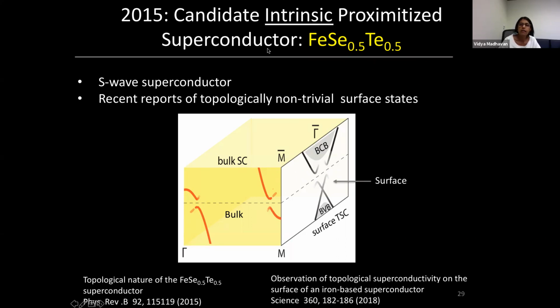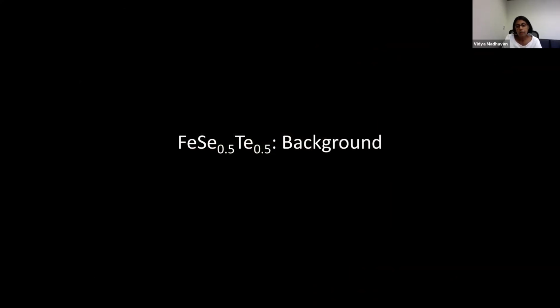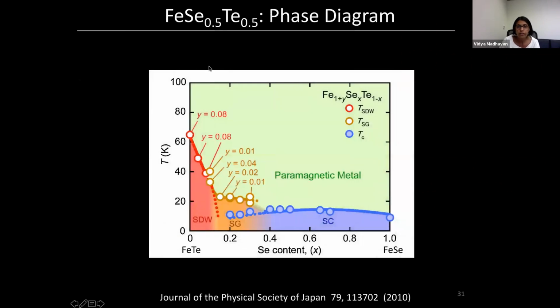So we've known for a long time that this material is an S-wave superconductor. So in the bulk, it's a superconductor. But what they found in 2015 is that it's also topologically non-trivial. So that means that this material on the surface has these interesting surface states that I was telling you about. So in one material, you have both superconductivity as well as the presence of these two-dimensional Dirac fermions on the surfaces. So one imagines that if one could turn on a magnetic field and look at the vortices in this material, you should be able to actually find Majorana fermions. Okay, so before I show you the experiments, let me just give you a little bit of background on the system. So this is the phase diagram.